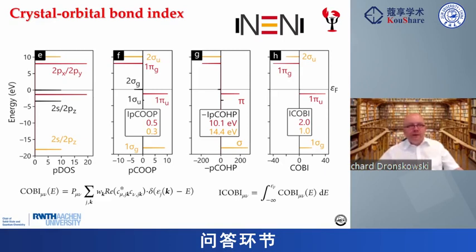If you look into the paper, and particularly the supplementary material, we show a COHP plot, and then you immediately find that there is no sodium-helium bonding, no helium-helium bonding, no sodium-sodium bonding, but there's bonding between the sodium and the electrons, over a distance, and the distance is kept by the helium atom. It's a salt. Okay. Thank you.